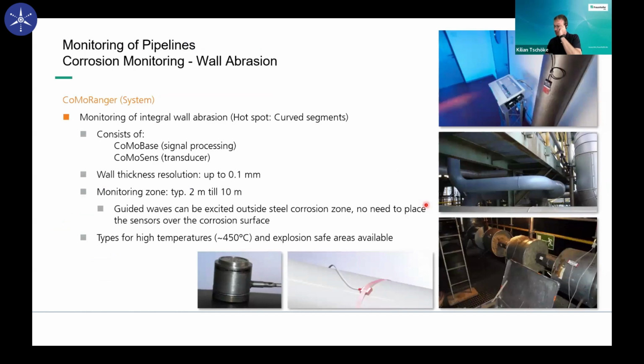for using this technique for monitoring pipelines. Pipelines under insulation in the best case for high temperature pipelines. But this is a really easy example for monitoring corrosion in pipelines. If you remember, we have a relationship between frequency and wall thickness and velocity of the waves. And you can fix the frequency because this is a parameter in your setup and your hardware.